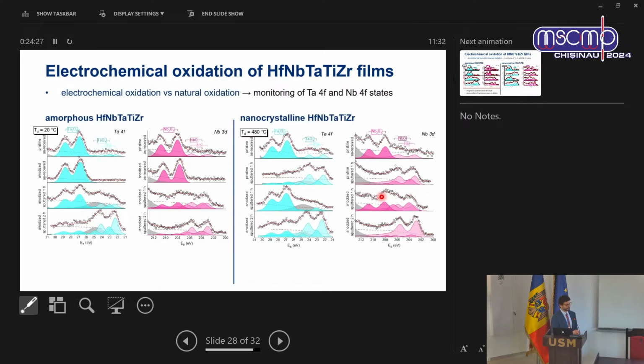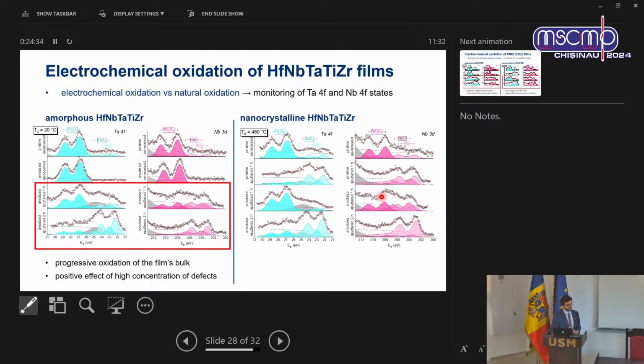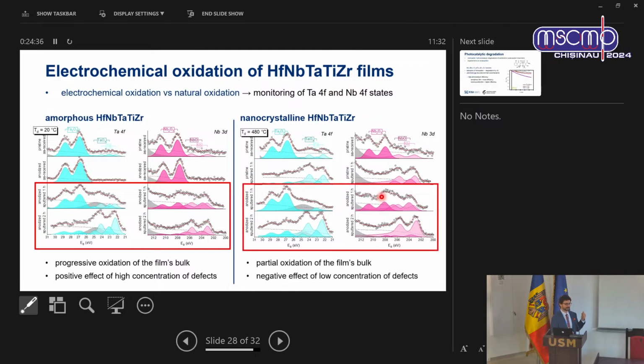And just to compare the effect of natural oxidation and of the electrochemical oxidation, you can see that in the previous pictures, the argon sputtering removes the oxide layer in these 2 elements, and they should be present almost dominantly in the metallic state. While in the case of electrochemical oxidation, there are still dominant peaks in the oxide states. That means it is really more effective to put it into electrolyte and oxidize it by anodization than just expose it to air for a long time.